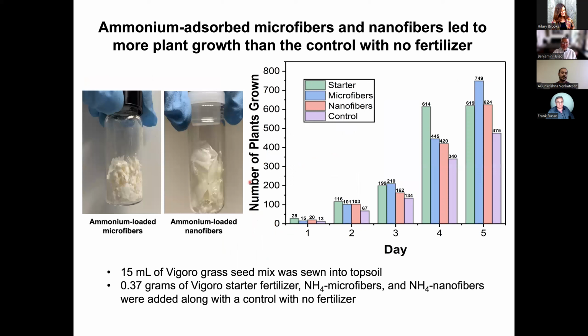So also after the removal, the ammonia absorbed microfibers turned out to be a wonderful fertilizer because it really has a sustained release profile. And this is a starter. This is our ammonia absorbed microfibers, nanofibers, and control. Control means there's no ammonia at all, just the nanofibers. And we actually found out the microfibers perform the best. And the reason for that is because the nanofibers sometimes can be lost in the soil. Microfibers really give you a controlled release profile.